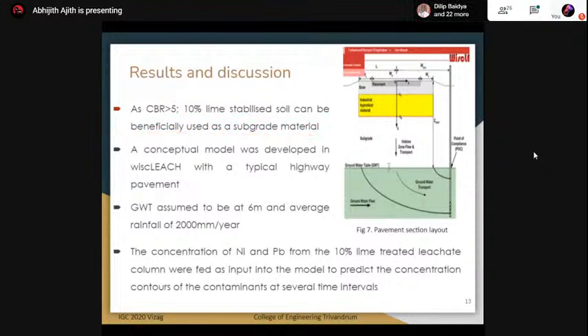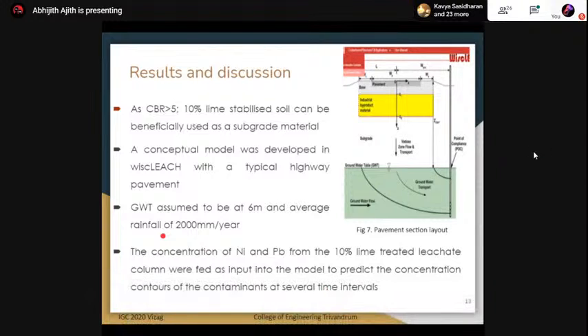As a conceptual model, a model was developed using the software WiscLEACH with a typical highway section, utilizing the stabilized dredged material above the subgrade, in this layout. The properties and dimensions were all taken as the default values from the software itself. The groundwater table was assumed to be 6 meters, and the average rainfall was taken as 2000 mm per year. The concentrations of nickel and lead from the 10% treated leachate columns were fed as input into the model to predict the contour concentration map of the contaminants at several time intervals.